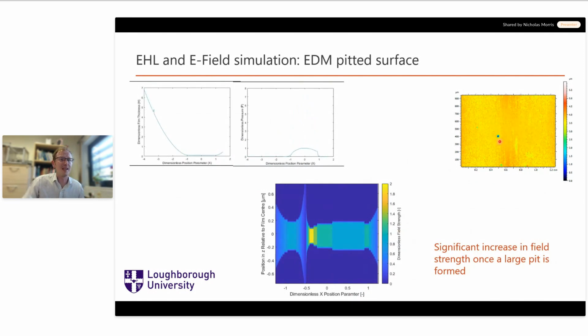So this would be an EDM pit that you can see on the figure up here. And if we take a cross section of that and allow the EDM pit to move through a representative EHL contact, we can see that that EDM pit on its own can cause a 2 times increase in the field strength with comparison to the smooth EHL contact that I showed on 3 slides back.